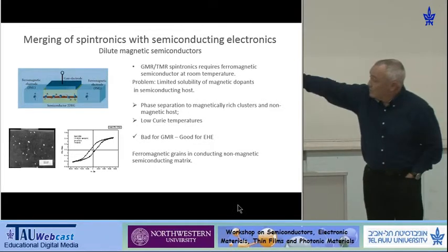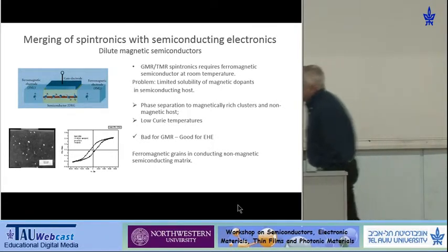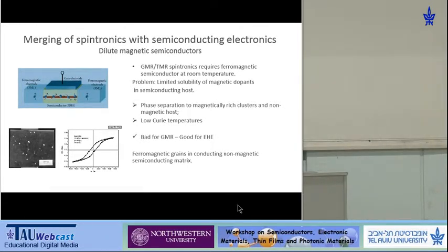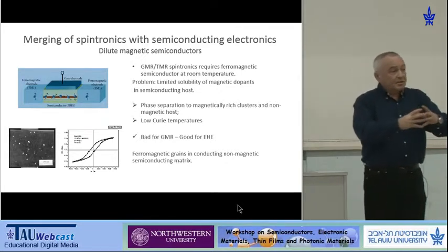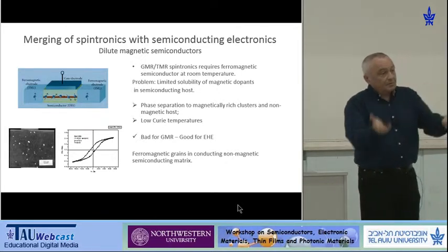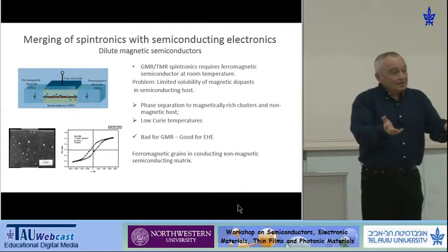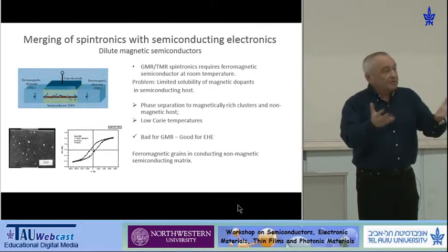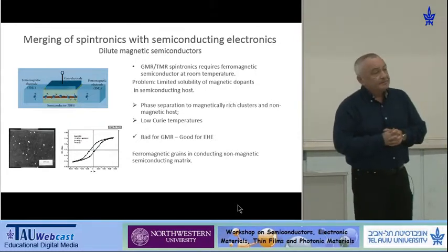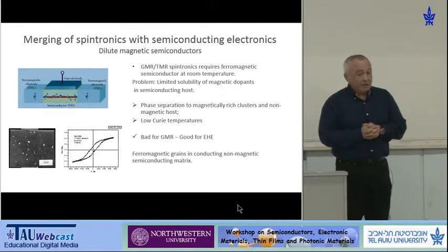So this is room temperature, well, maybe not room temperature, but this one is, I don't know, 300. But this is only a question of the size of the cluster, because the blocking temperature depends on the anisotropy energy multiplied by the volume, and that's what gives you the energy. So you want to use these clusters then? Yeah. You want to use them?